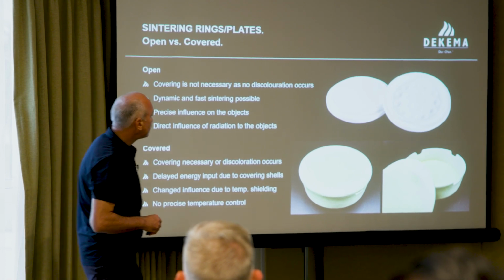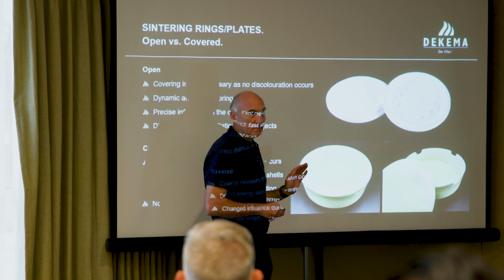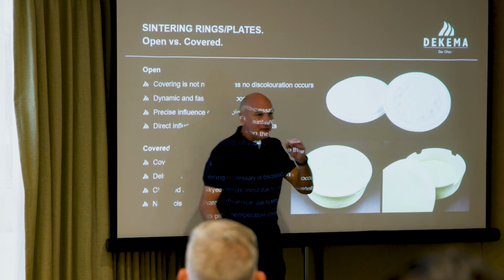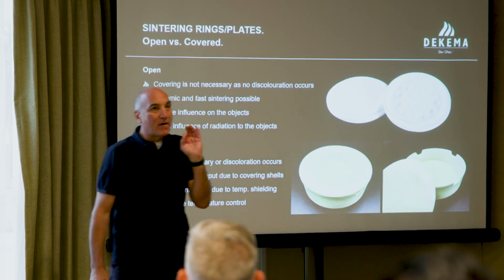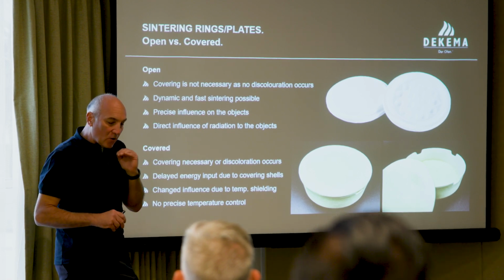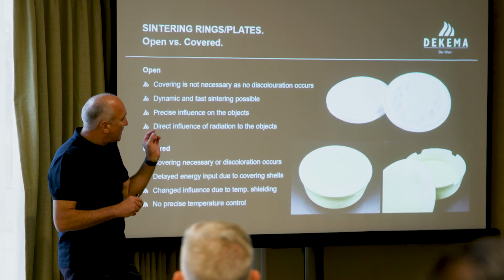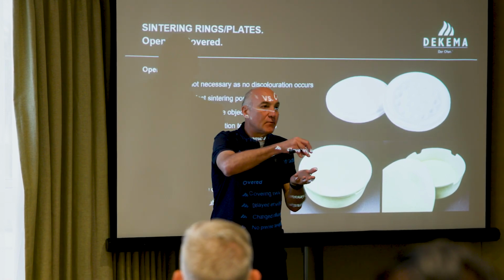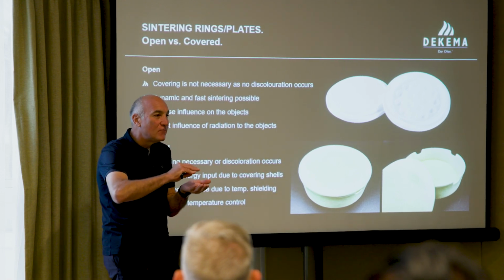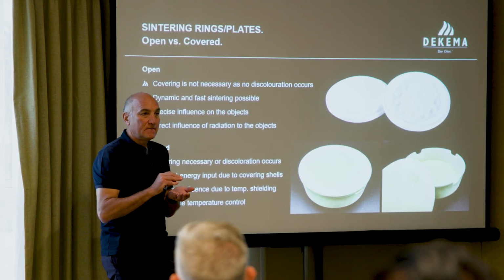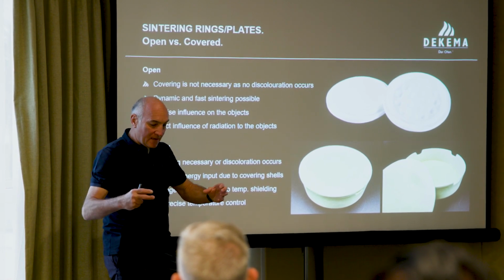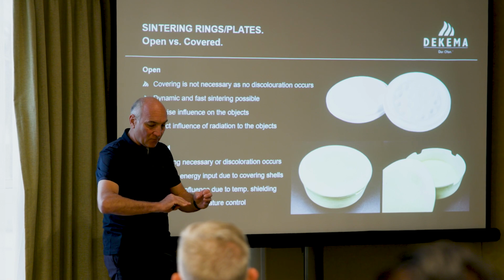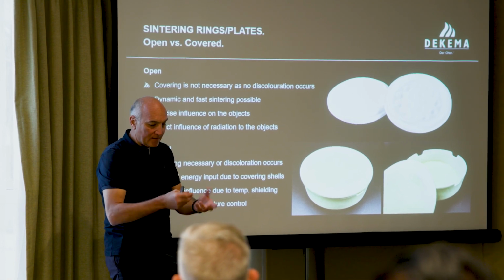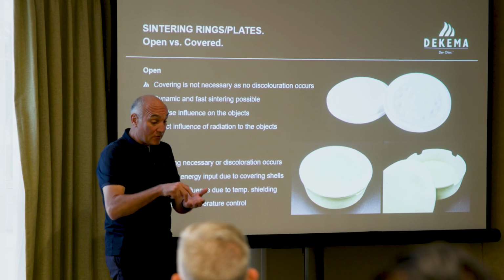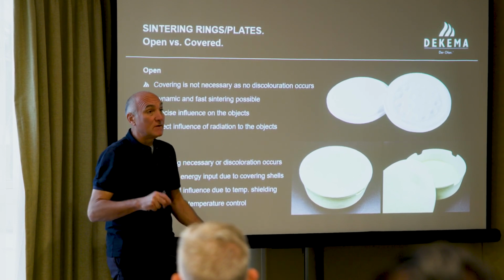What we suggest is using so-called micropearls. We have pearls with a very small deviation, around 0.5 millimeter small, and we only put one microlayer, one layer on this plate, and then the parts on top, because this is like friction-free movement for the zirconia. You have the perfect radiation input. The part can friction-free move on this one layer of micropearls, and it's finished. I don't even mind whether you put your large spans like this or like this.